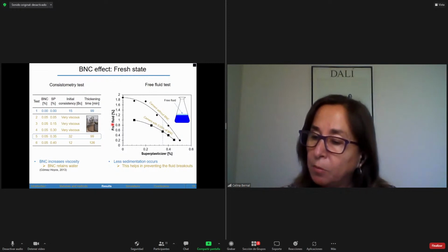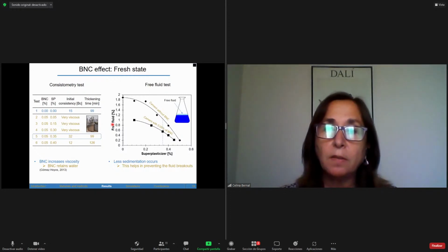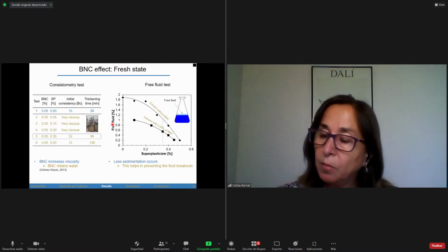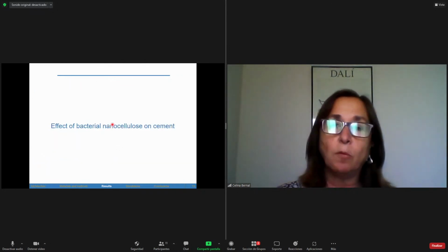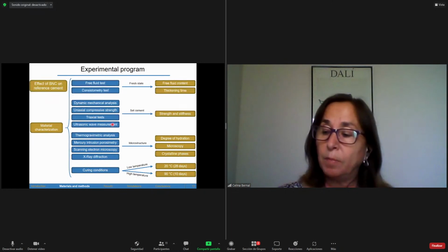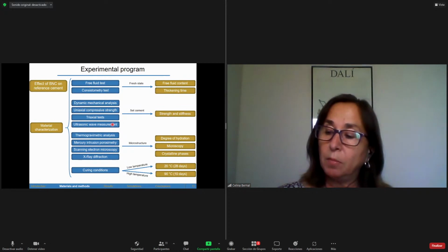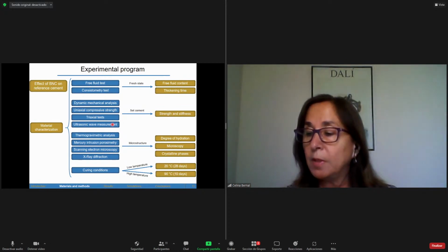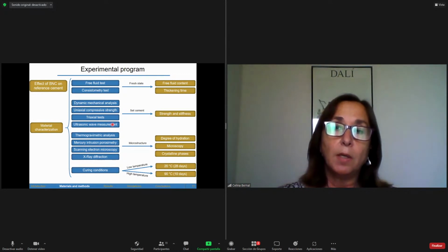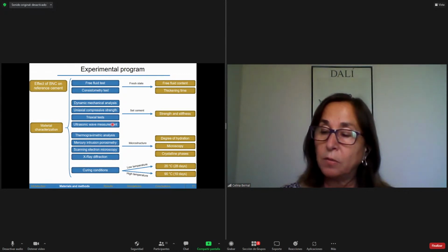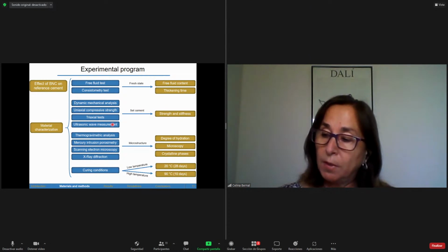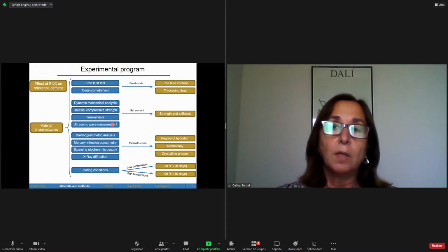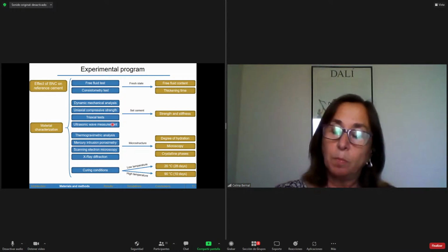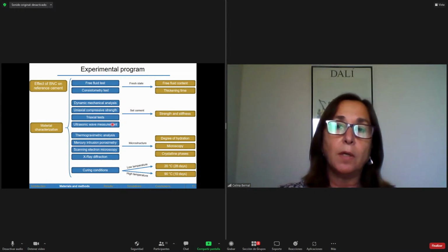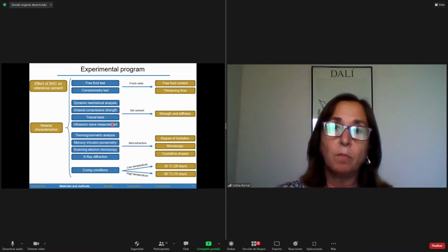Another thing is about dynamic mechanical analysis. You found that for the lowest content of bacterial nanocellulose, the stiffness decreased, and with higher contents of bacterial nanocellulose, the stiffness increased. Can you explain this effect, or do you have an idea to explain this effect?